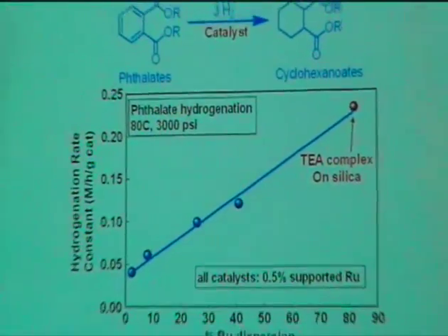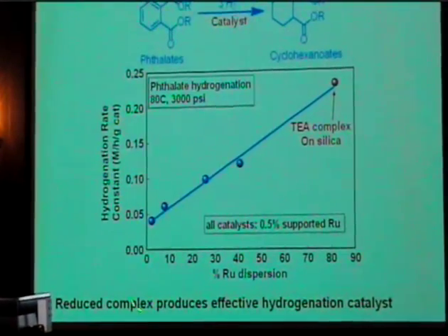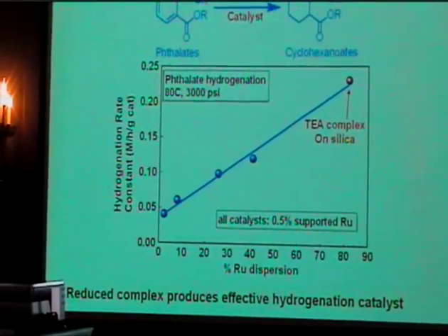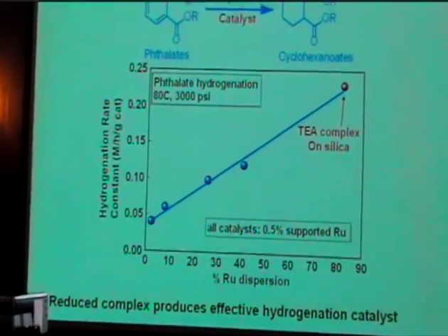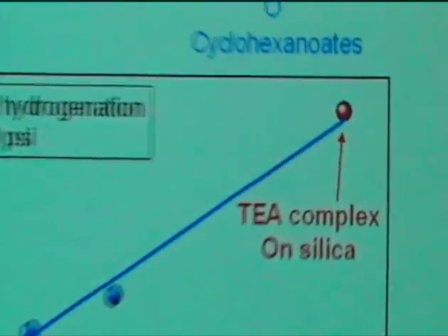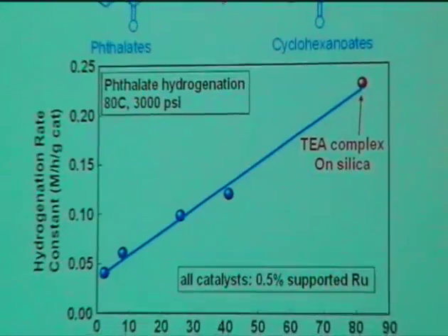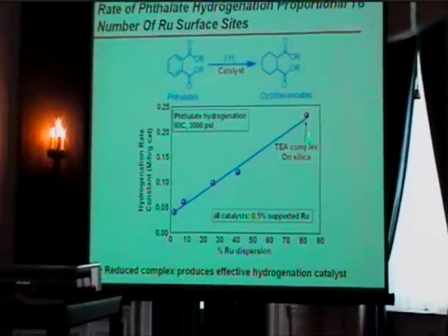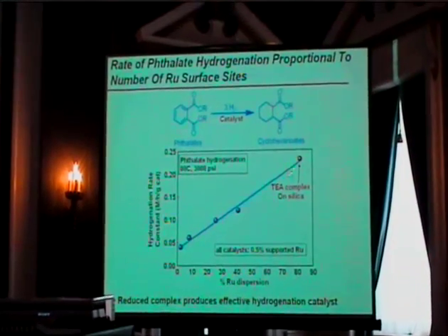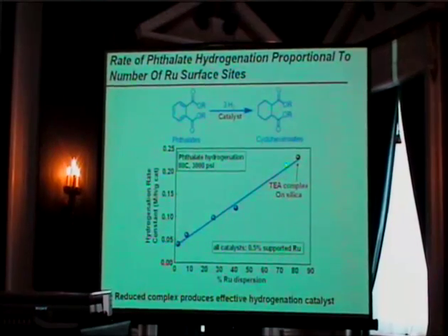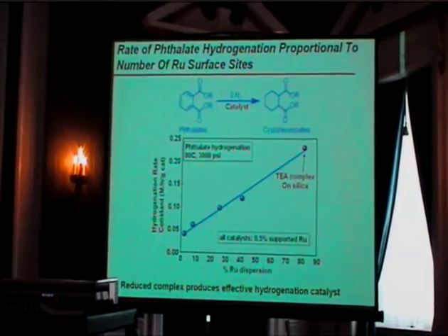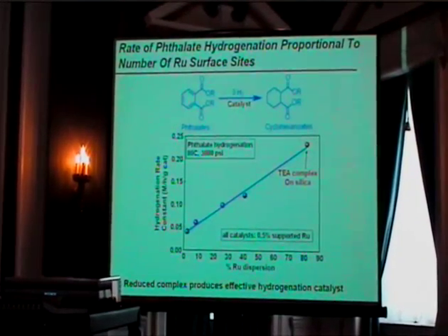And so we're getting a rate which is proportional to the percent of dispersion. So being at the same loading level on all of these, we're essentially measuring the rate versus the number of ruthenium on the catalyst surface. And so we have a very nice correlation here. That doesn't always happen. There's no acid site or anything else that's getting in the way of the metal catalysis. So that's dominating, and the catalyst made by reducing this complex behaves very well. In fact, it's extremely good for this reaction.